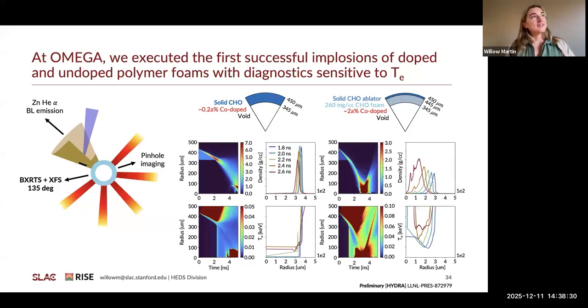So it depends on a lot of different factors. I proposed experiments at MEC first for a few different reasons, but there I wanted to do an experiment that explored a wide range of plasma conditions. And that's why, for this particular MEC experiment, we proposed at LCLS to use the short pulse laser, because we were trying to validate the performance of fluorescence spectroscopy as a diagnostic, but in a very new temporal regime for that diagnostic to be applied. And there was an additional challenge that we faced in being ill-constrained and being able to predict the plasma conditions that we would generate.